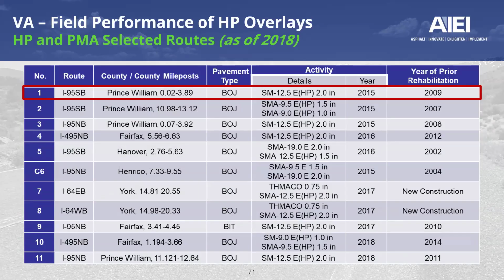But then, starting in 2015, you see that the technology was employed on a lot of interstates. So in this table, for example, we're compiling the various routes and sections on which HP was used to mitigate reflective cracking, except one where we did have a bituminous material on top of an existing asphalt. These are not all projects that VDOT has constructed. This list is as of 2018. There were about double of these sections constructed between 2019 and 2025.